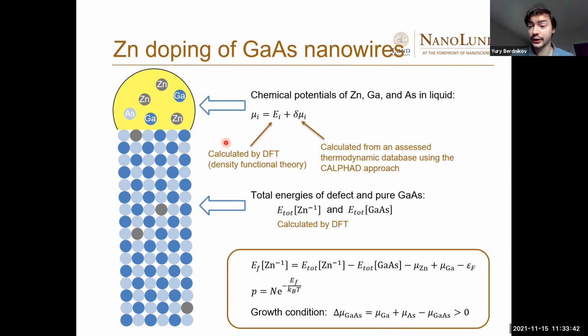May I have a question? As I remember, there have been quite a lot of attempts at doping horizontal gallium arsenide nanowires, planar, in Illinois. What they observed were oscillations of the nanowire diameter as soon as they add zinc. But their system is quite specific because they get planar growth of the nanowires. Is it selective area growth? No, that's not selective area growth. It's just gold catalyzed growth where they deposit the droplets, and these droplets spread on the gallium arsenide surface. Such crawling. So in these crawlings, as I remember, they get this effect.